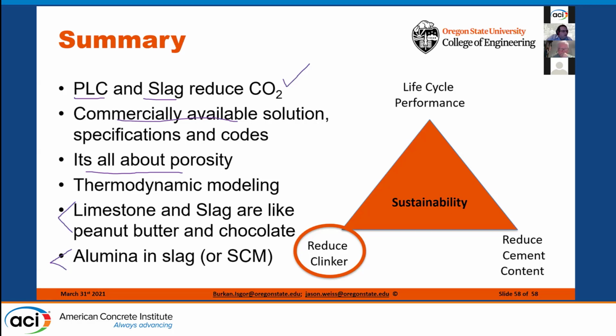So the interesting thing is, I'll try to answer some of these questions and then add a little bit of context to this. We did look at a couple different ashes, and I would have to get back to you with the exact alumina contents of those ashes. The ashes are much more variable than the slag. The slags are very, very consistent in terms of their reactivity and the benefits that you see.